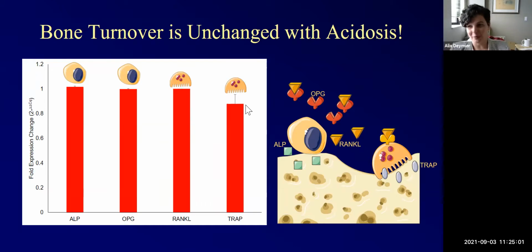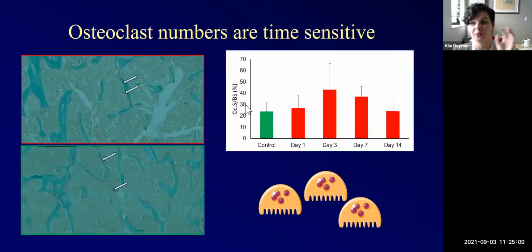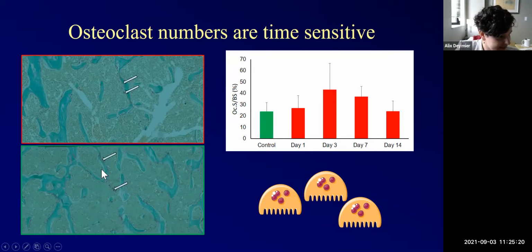So I say, okay, well, maybe there's something with the TRAP. Maybe it's time dependent. So what we did now is we took bones from day 1, 3, 7, 14, and controls. And we stained them using a stain that stains for osteoclasts, so bone resorbing cells. You can see these little purple dots here. Those are osteoclasts. We counted how many of those we had per area of bone. That's what we have here. And what you see is that indeed, between control and day 14, there's no change. Whew, my RNA data makes sense. But at day 3, I have an increase.